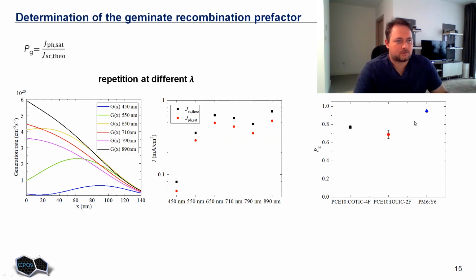We got these values. We see that for instance for PCE10 with COTIC-4F, we get about 80% of all excitons actually split into free electrons and holes, which is not bad, but could be better. For instance, this high performance system has something around 0.95. So almost all photo-generated excitons can be split into free charge carriers.